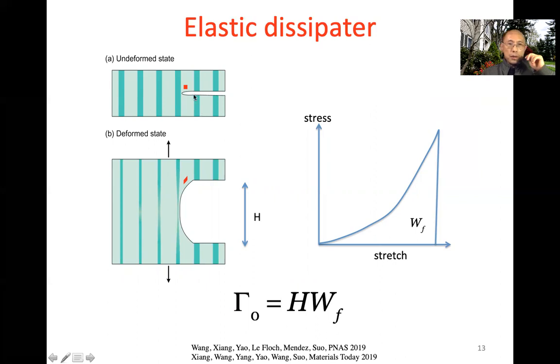Now, if I cut a crack, let's say I mark a material particle by a square. When I apply a load, the matrix is so soft, it can shear dramatically, allowing this crack to blunt much more than before. So this blunting, I call H. Then your toughness will scale with this H. Scale so that the toughness is this opening, and WF is a stretch curve all the way to fracture, the area under this curve.